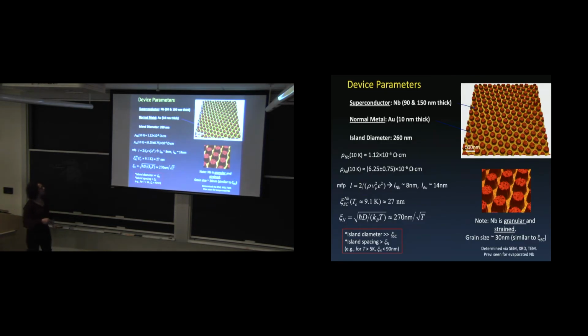Also to note some of the important parameters of our system. The niobium is very thick and the gold is very thin, and we've done measurements and other things to show that we're not decreasing the transition temperature of niobium because of the gold, which can happen if they're relatively thick or thin compared to each other.